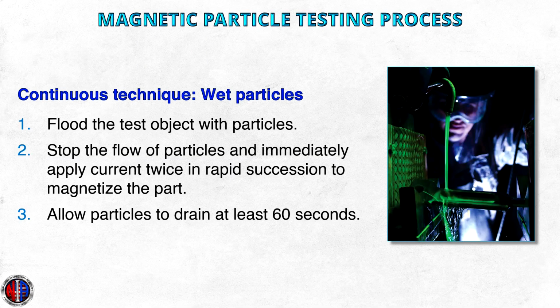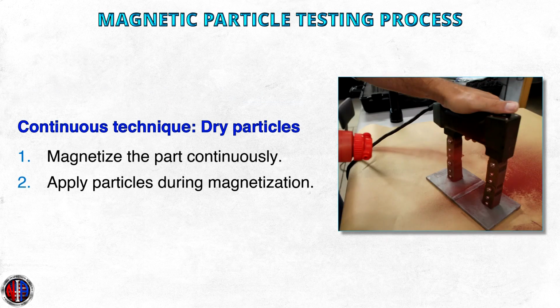When using wet particles in the continuous technique, the process is very simple. 1. Flood the test object with particles. 2. Stop the flow of particles and immediately apply current twice in rapid succession to magnetize the part. 3. Allow particles to drain at least 60 seconds. The continuous technique for dry particles. 1. Magnetize the part continuously, meaning that we are keeping the magnetism flowing through the test object while we do 2. Apply the particles during that magnetization.